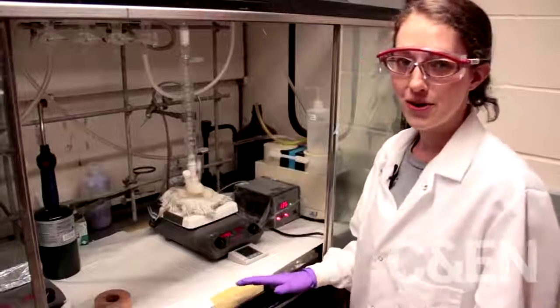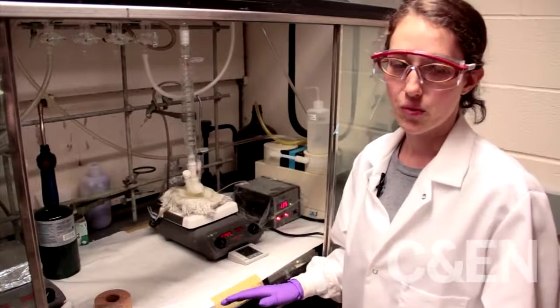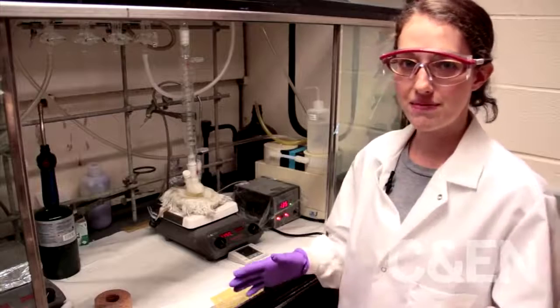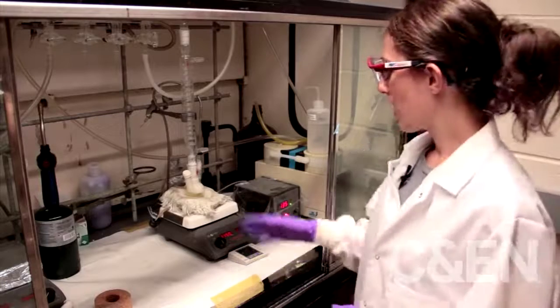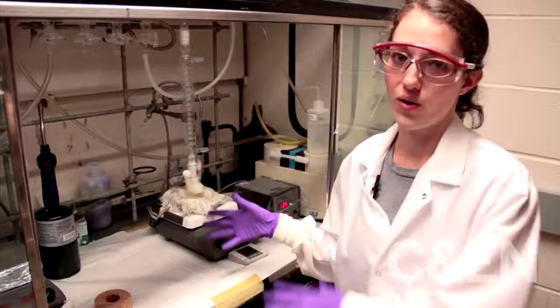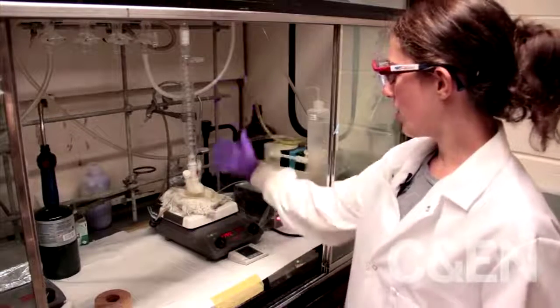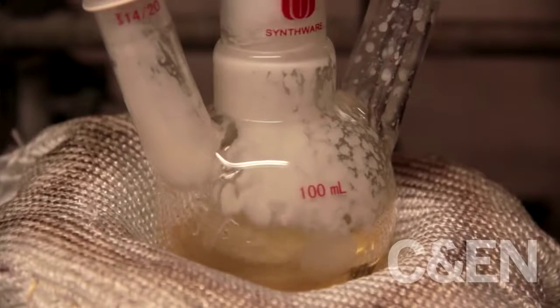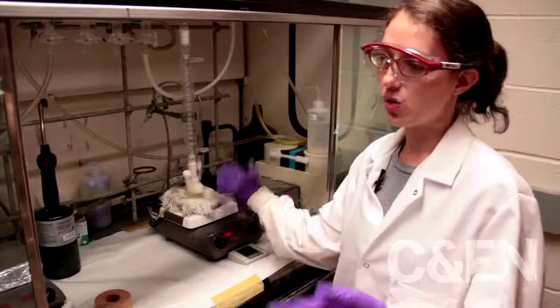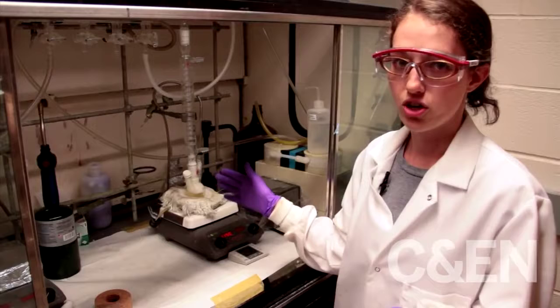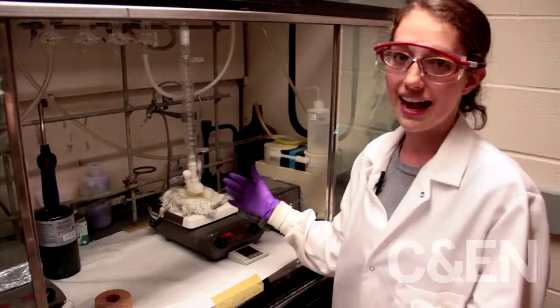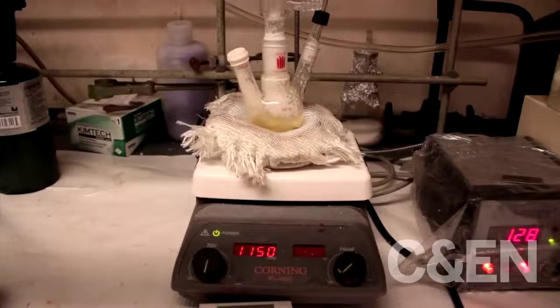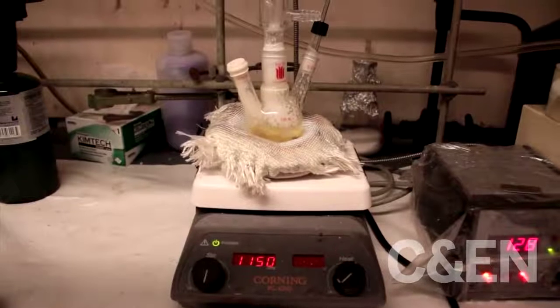So in our group, we make and use quantum dots, which are cadmium selenide nanoparticles. Today I'm going to start out by showing you how we make them. In here we have some stearic acid and cadmium oxide that we heat up to dissolve the cadmium oxide in the stearic acid. And then we cooled it back down and added some trioctylphosphine oxide and some hexadecylamine.